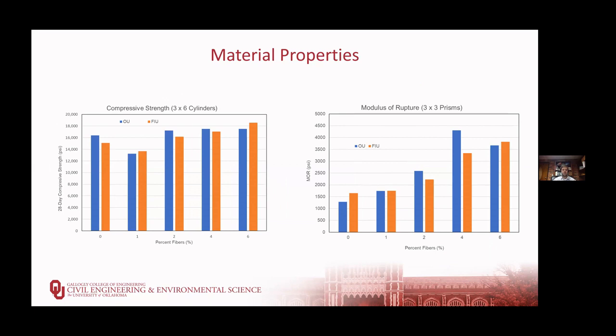In looking at compressive strength, again, OU materials are shown in blue, materials from Florida are shown in orange. We had a compressive strength in the range of about 16 to 18,000 PSI. We saw a little bit of an increase as we increased steel fibers in general. We did see a decrease with the 1% fiber mix consistently, but once we went on to 2%, 4%, or 6%, we saw a modest increase in compressive strength. We saw an increase in flexural strength as we increased the steel fibers, which is to be expected. And in both cases, we saw fairly similar performance between materials available in Oklahoma and those available in Florida.